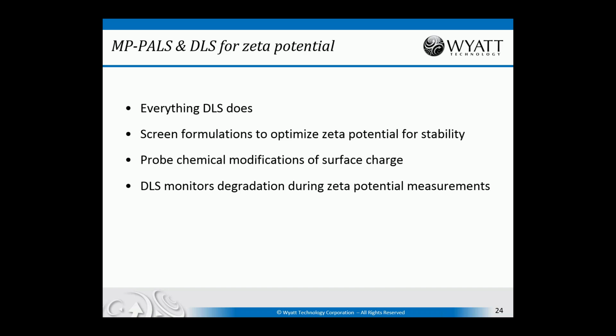And finally, there's another unique property of the Mobius compared to most other PALS instruments, in that it measures the DLS simultaneously with the MP-PALS, which means that we're measuring the zeta potential simultaneously with size. So if something happens to our particles as a result of applying the electric field, we will immediately see that in the size measurements, which are taking place simultaneously. So any type of degradation that occurs during the measurement is immediately picked up.